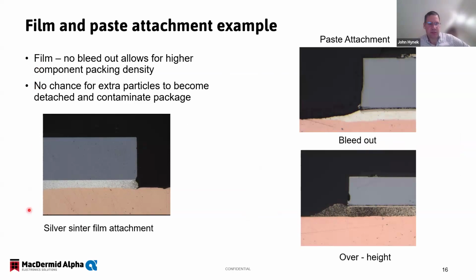So this picture here is a silver sinter film attachment, and you can see a very nice edge here where the film just cut very nicely, didn't bleed over. There's no issues. It's just straight in line with the die.